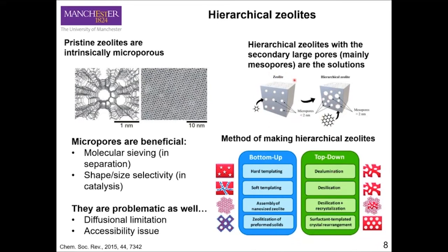Top-down means we do the normal synthesis of zeolite to have the bulk zeolite first, and then we do post-synthetic treatment to try to generate the large pores. This method is very practical because it's used heavily by industry, as it's quite cost effective. The bottom-up approach normally uses templating, especially soft templates. They are very effective in giving us beautiful materials, but they're quite expensive. Some of the soft templates need special synthesis and can only be produced in small amounts. Most importantly, after the scaffolding, we have to remove them, and the calcination of the synthesized zeolite can give us some very toxic flue gas, which is not ideal.